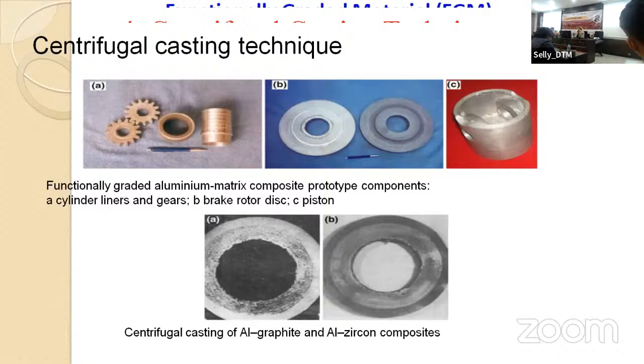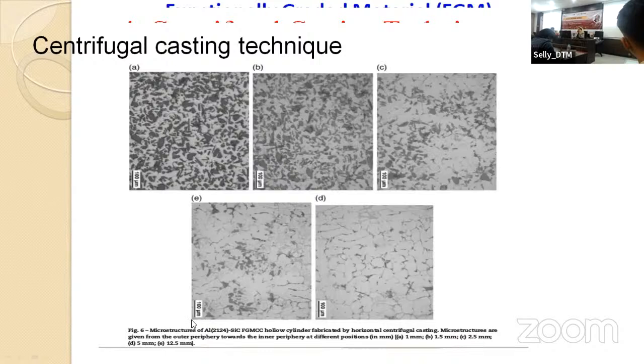I want to show you its SEM analysis. You can see in the microstructure the aluminum silicon carbide hollow cylinder fabricated by the horizontal centrifugal casting method. So they took into consideration the experimental data, which differ from the outer periphery towards the inner periphery in different positions. You can see at the outer, of course, the particles are crowded. You can see the inner part, yes. And we take into consideration the transition region. It's important for us.